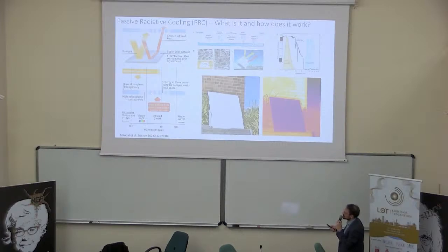Our atmosphere has some peaks, windows where it's possible to spread out this temperature directly to outer space. So we can exploit these materials to have a maximum emissivity. Here is this range that is going from 8 to 13 micrometers. And this is expected.